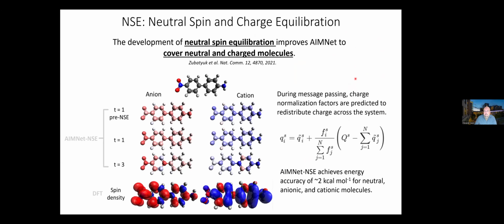Again, I'll talk a little bit about how neutral spin equilibration works, and show you a cartoon representation of why it's important. Essentially, it allows us to reproduce these non-local effects. For example, if you take this conjugated organic molecule, you either attach or detach an electron from it. What DFT tells you in terms of the spin density is the formation of this spin density wave-like behavior with plus and minus phases.